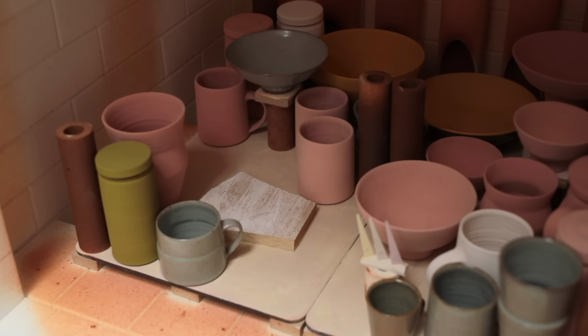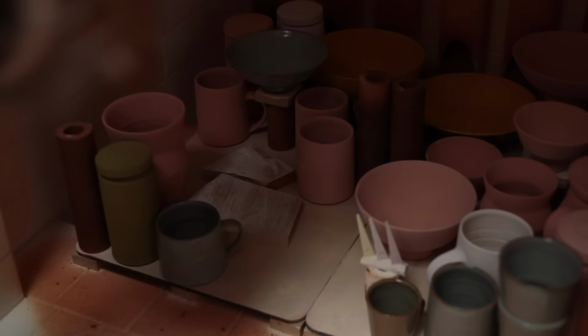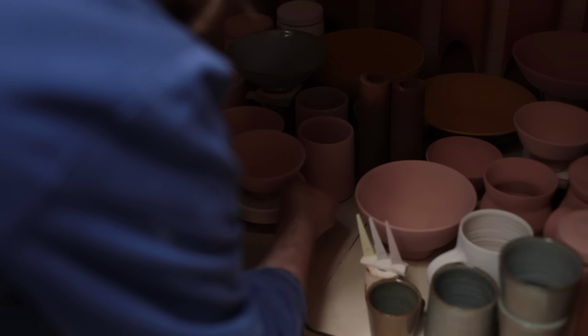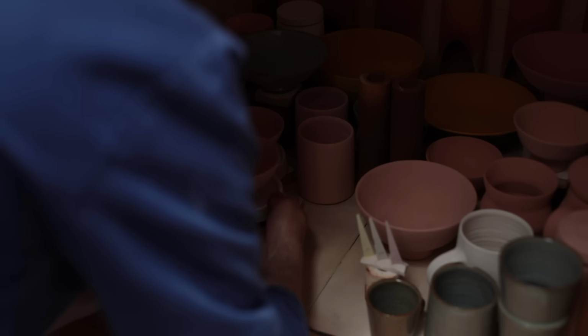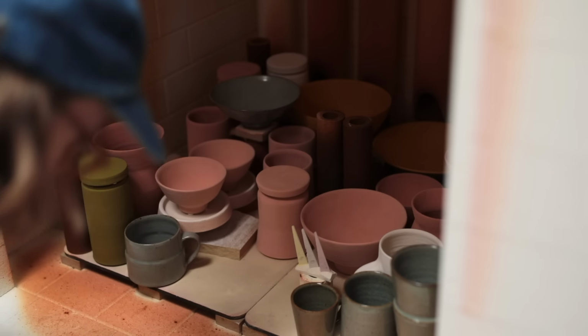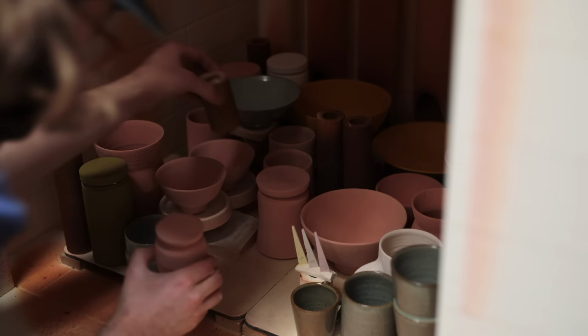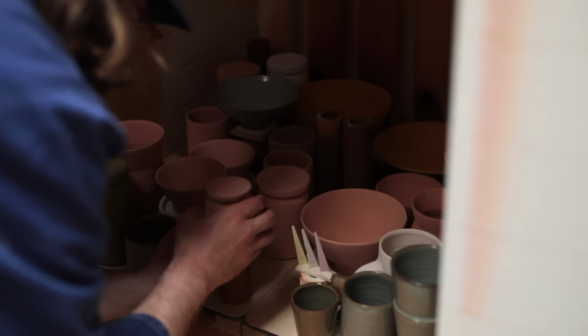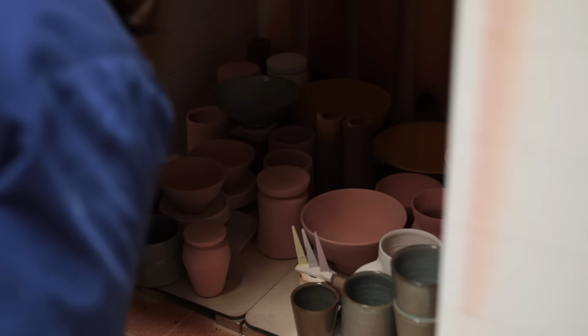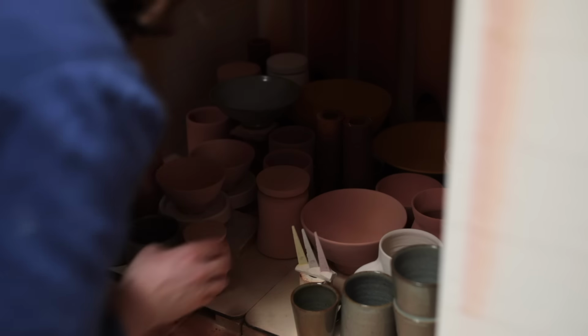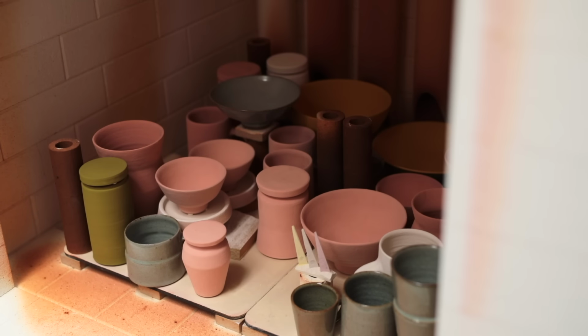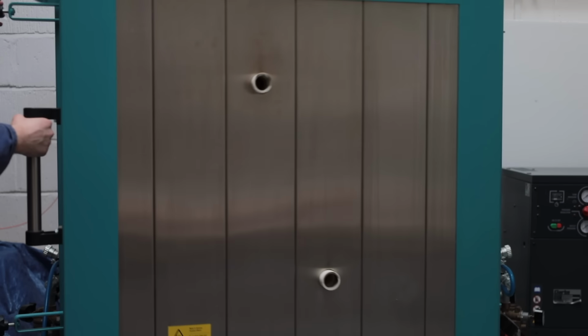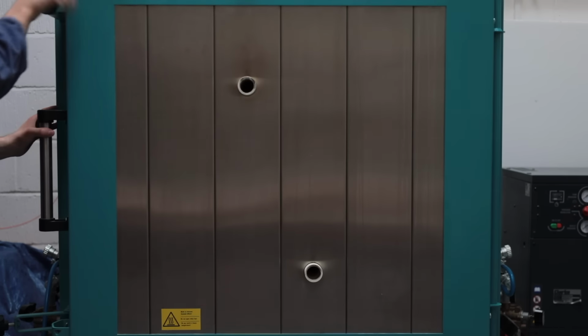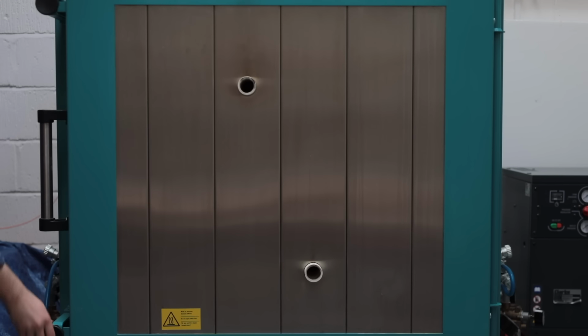This is my Rohde KG-340 gas kiln, which is fueled with mains gas, and it's that which allows me to fire in a reduction atmosphere, which is something my electric kiln cannot do. Being able to fire in a reduced atmosphere opens up another world of colour and texture, and in this instance that will change the copper and the iron drastically, as compared to if you were to fire the same materials in an electric kiln. So please do bear that in mind if you're doing experiments like this. The ways metal reacts in both atmospheres is very different, and what comes out of this gas reduction fired kiln will not be the same compared to if you fired the same metals in an oxidized atmosphere to the same temperature.